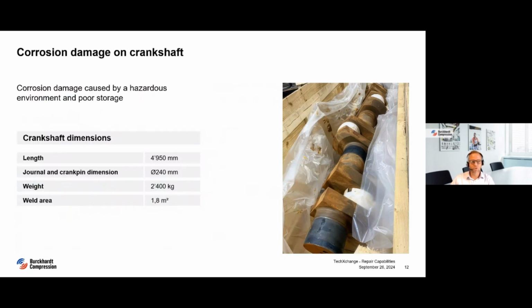As you can see on the photo, we received at our facility BCNL in Schiedam, near Rotterdam, the crankshaft heavily corroded, caused by hazardous environment and poor storage. The crankshaft has a length of 4,950 millimeters and a weight of 2.4 tons. This crankshaft has 7 main bearing pins and 6 crank pins with a diameter of 240 and a length of each pin of approx 185 millimeters plus the conus. That means we have a weld area of more than 1.8 square meters.